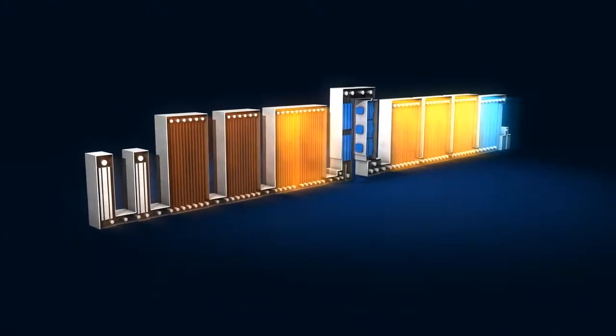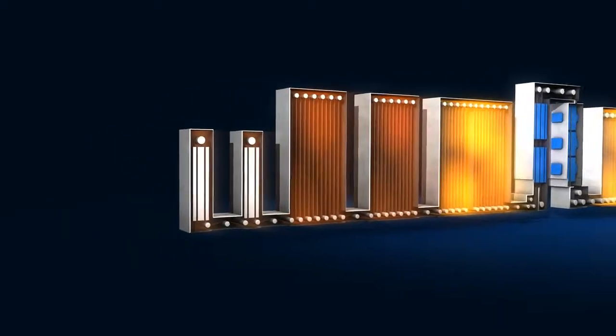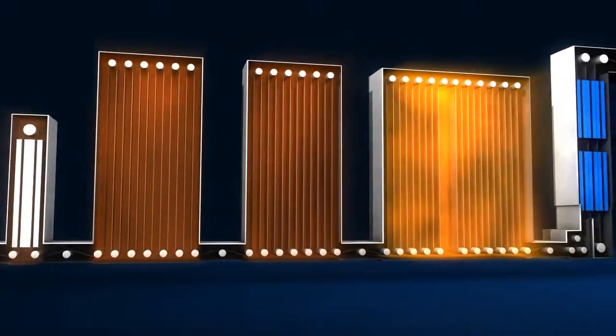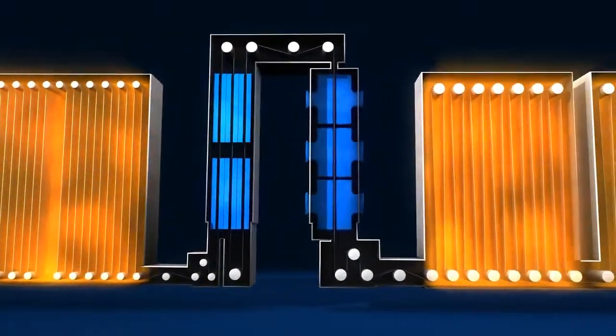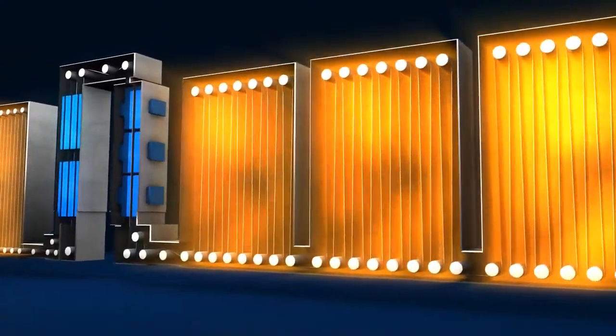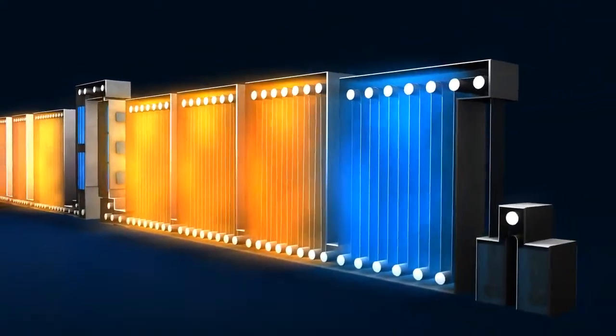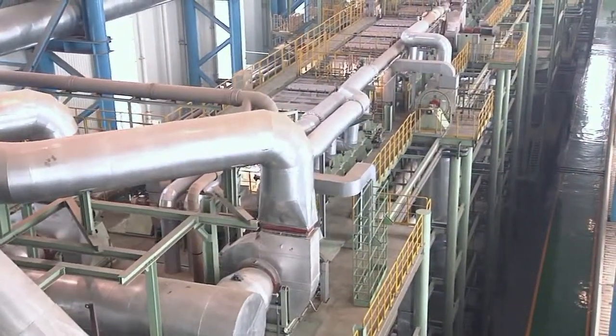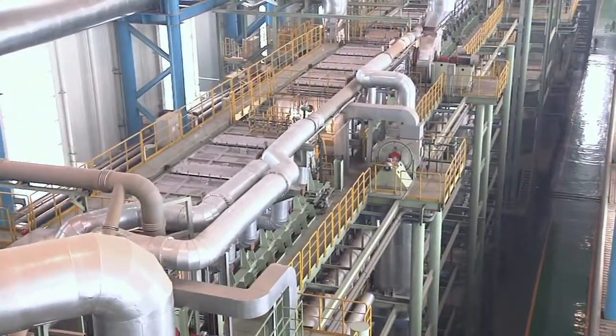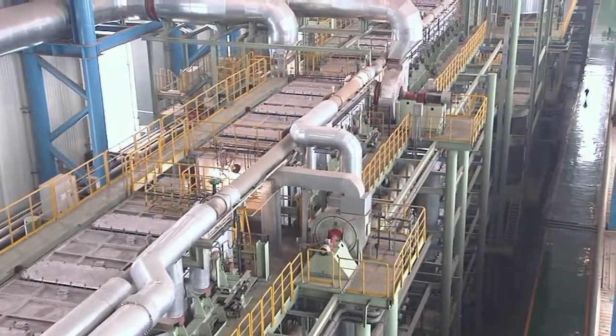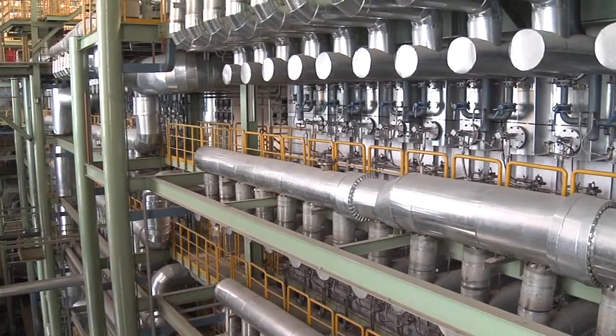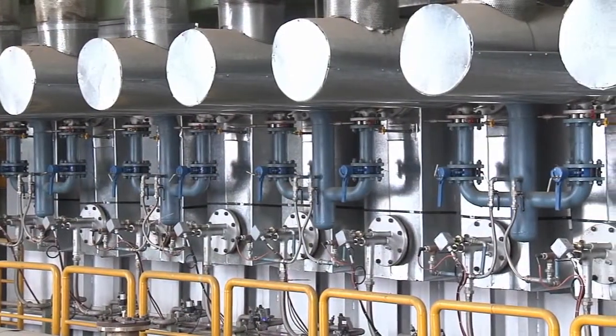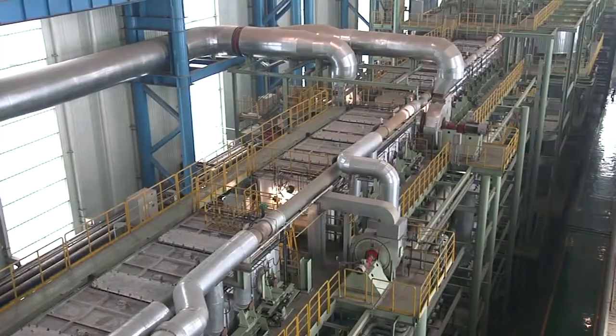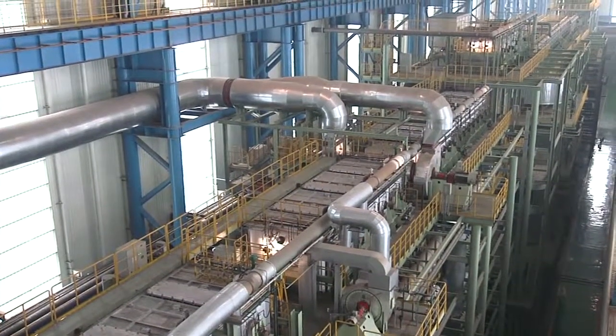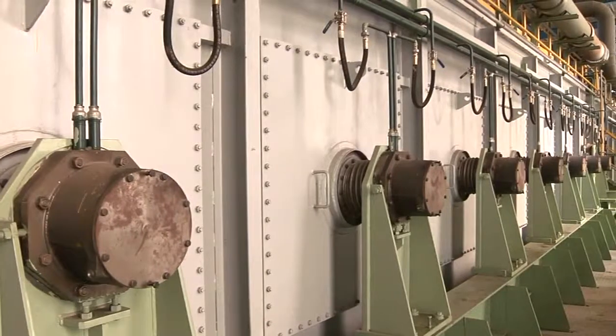The annealing furnace. It consists of the preheating section, the heating section, the soaking zone, the slow cooling area, the fast cooling area, overaging, the final cooling section, and the water quench system. In the heating zone, the strip is heated to between 730 and 850 degrees centigrade, depending on the steel grade. The strip is now glowing, that is annealed, giving the process its name.